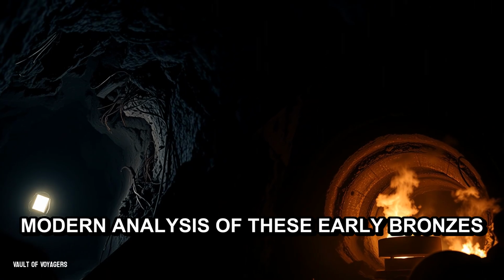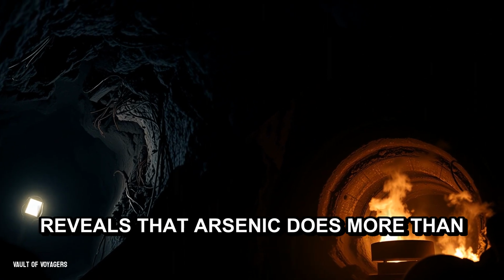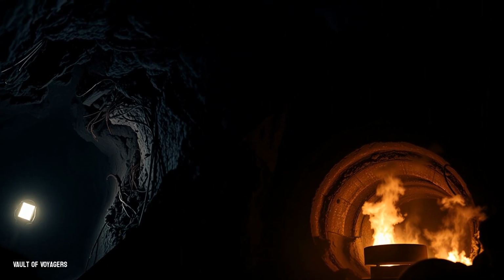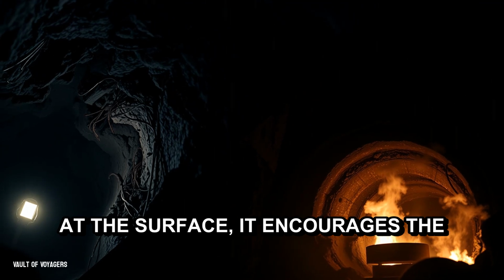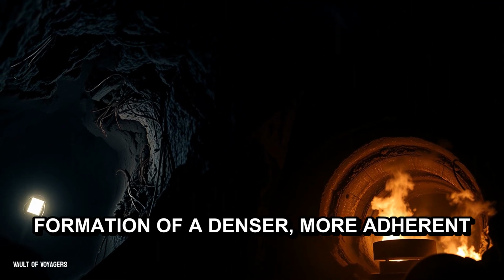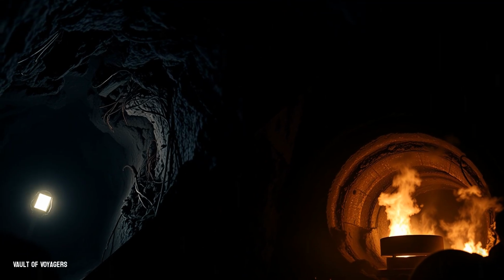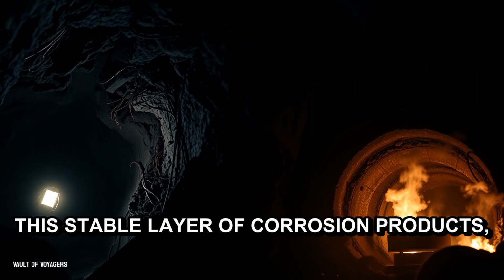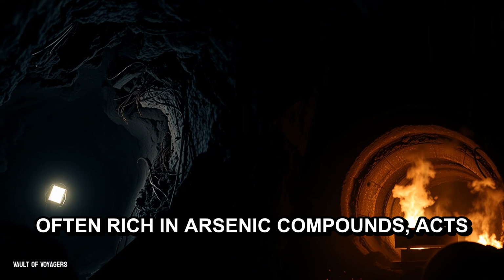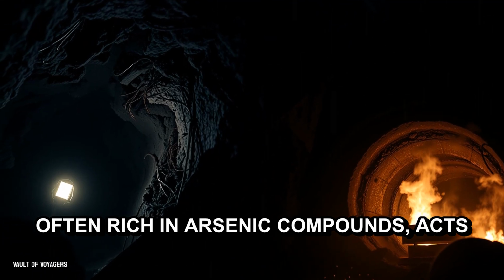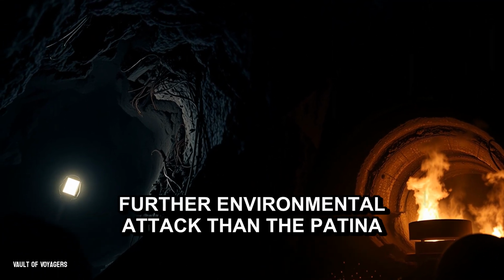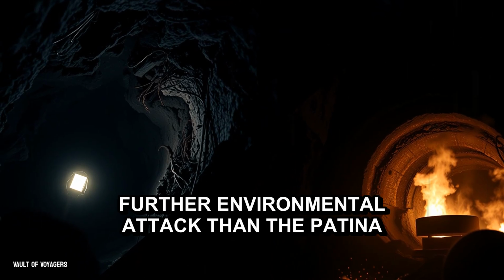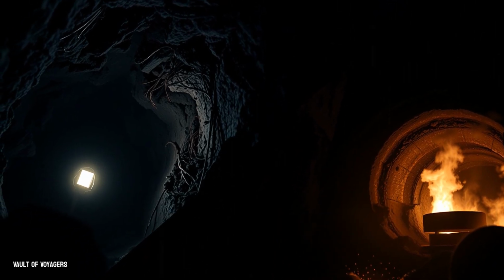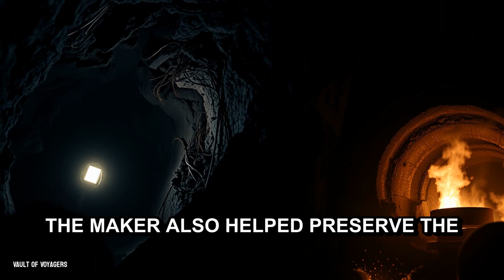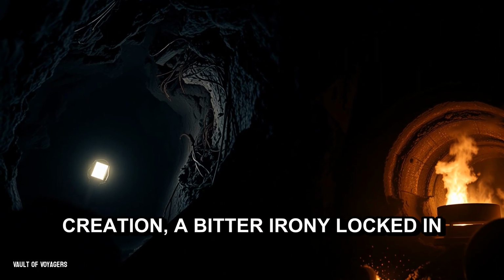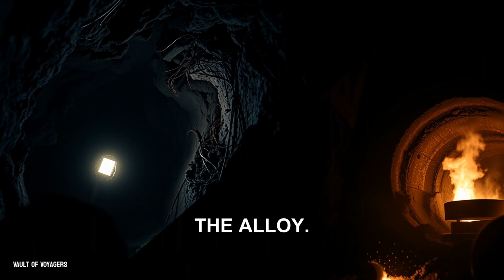Modern analysis of these early bronzes reveals that arsenic does more than just harden the metal. At the surface, it encourages the formation of a denser, more adherent patina. This stable layer of corrosion products, often rich in arsenic compounds, acts as a more effective barrier against further environmental attack than the patina on pure copper. So the very element that endangered the maker also helped preserve the creation, a bitter irony locked in the alloy.